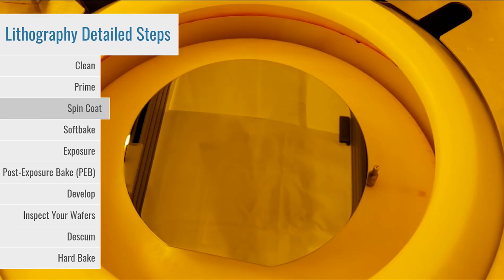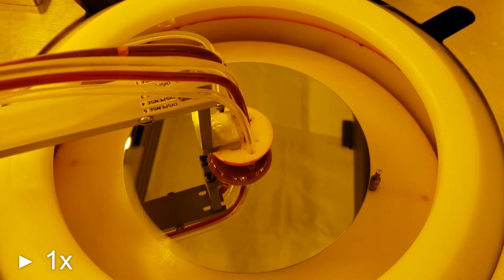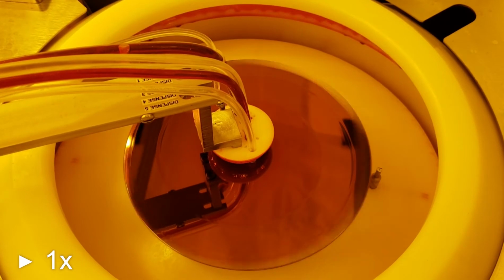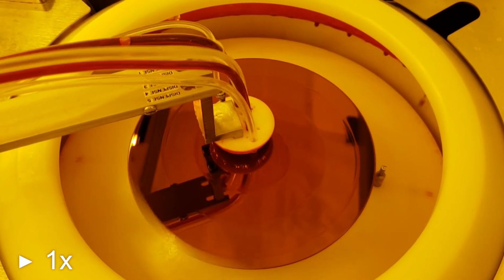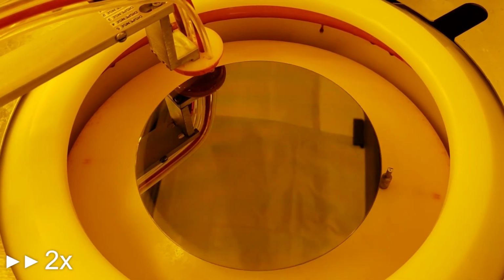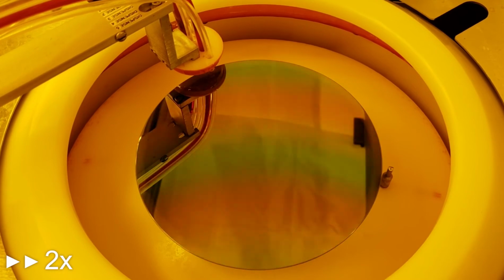During the spin coat step, liquid photoresist is dispensed onto the wafer and spun to the desired thickness. Here we'll see a typical spin coat process on an automated photoresist coat track. First, the wafer starts spinning, and the nozzle dispenses photoresist onto the wafer. The wafer continues to spin as the resist spreads to the edges. Then the spin speed is increased, and the photoresist continues to spread into a uniform layer.